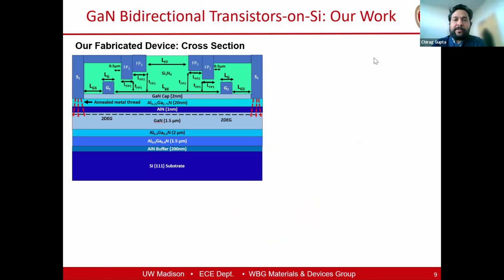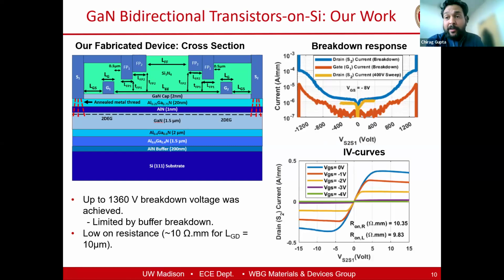So what we have done is we made these transistors in our research group, about 1.5 years back. We wanted to see these transistors in action. So we tried to fabricate the first set on GaN on silicon, because that's very common, and we saw in the literature that this is what people had done. This is the transistor structure, very standard. We just took a standard GaN on silicon HEMT epitaxial material. We deposited silicon nitride, and we did all these etchings to get these field plates in place to get the breakdown voltage. So basically, when we fabricated it, it looks like a bidirectional device.